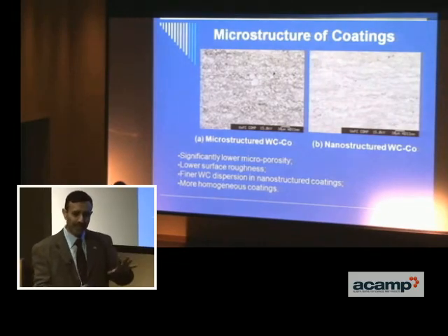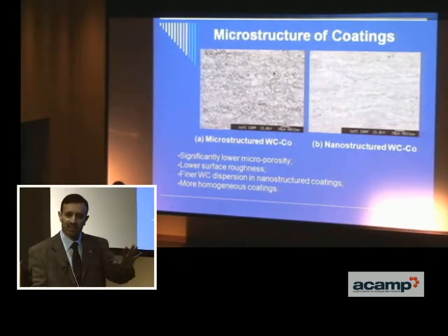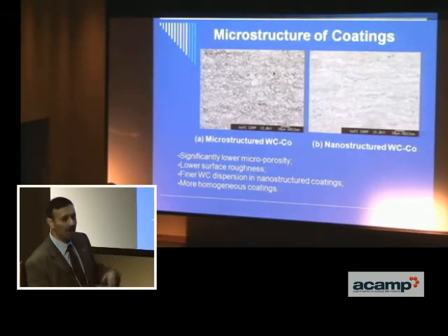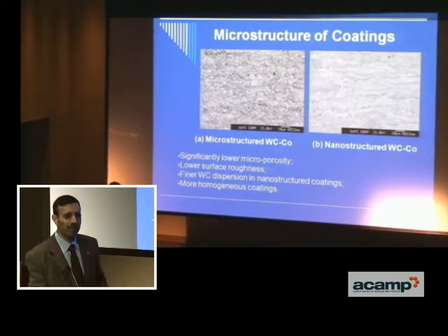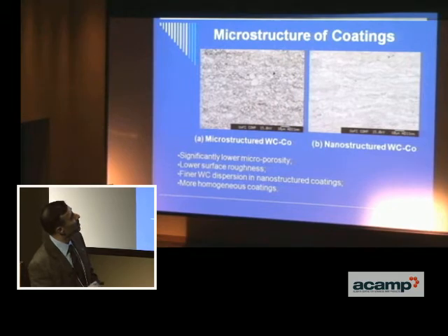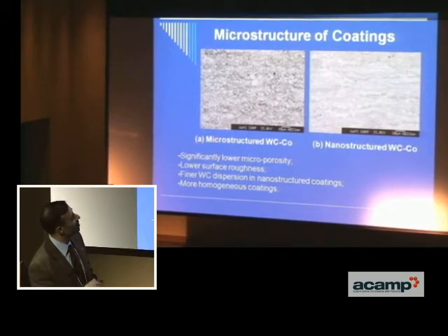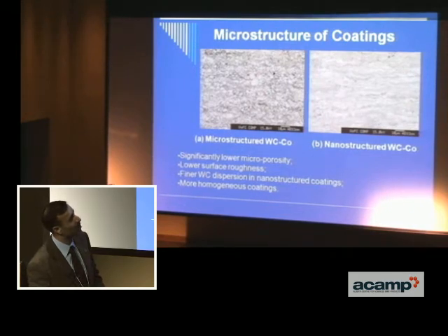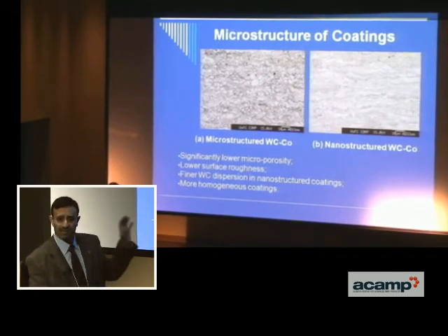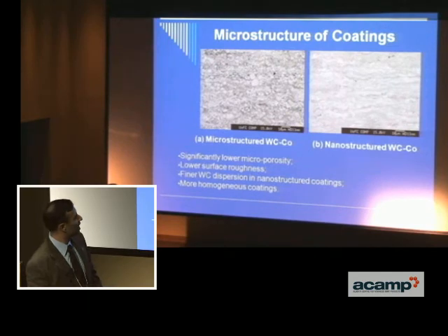When we've sprayed the material and it's sitting on the surface, when we cut through this coating and look at the microstructure, this is what we see. The microstructure here, the microstructured powder, and this is the nanostructured powder. There are some distinct differences there, what we tend to call homogeneity or homogeneous types of coatings.